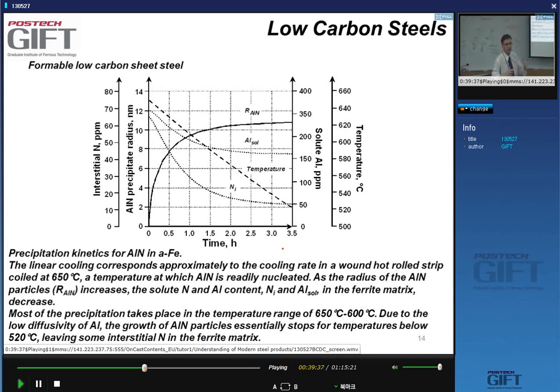But if the aluminum diffusivity is so low that it doesn't move anymore, the aluminum nitride will not grow. Or, if you look at the start of the growth of the aluminum nitride, it may not even nucleate. And you can see this here.